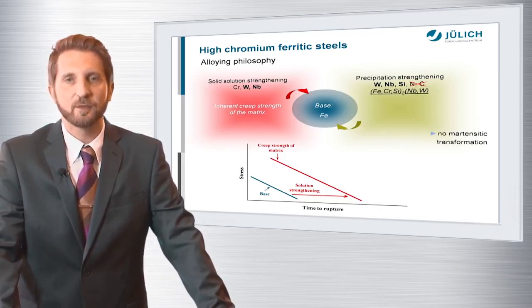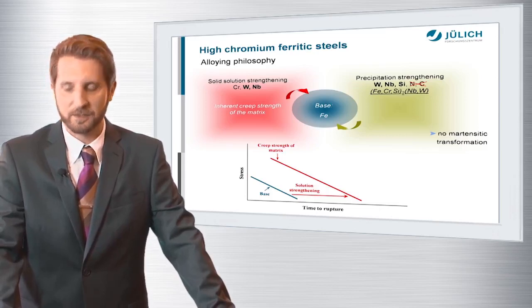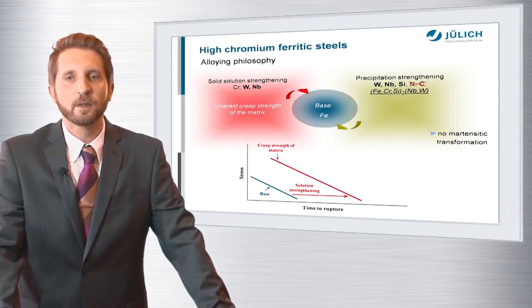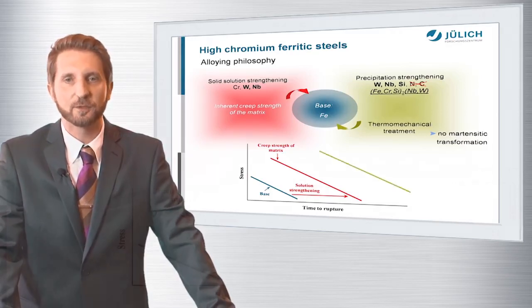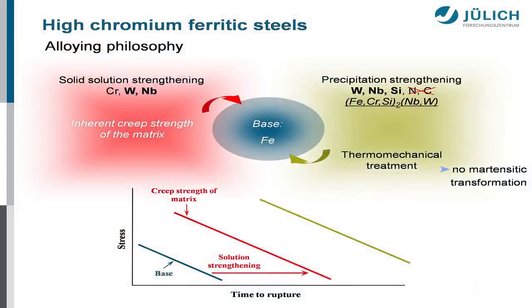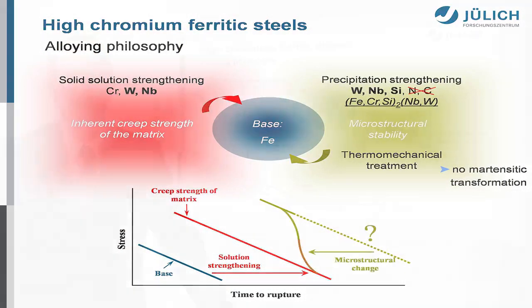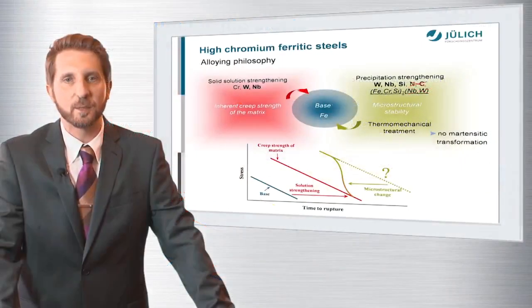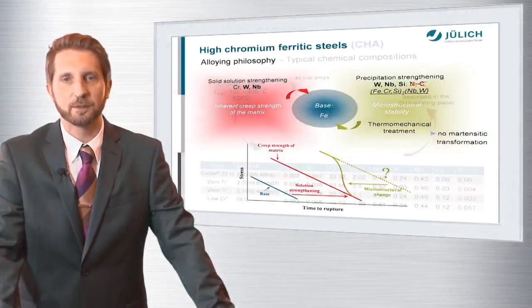And that means that if you want to go for enhanced dislocation strengthening, like it is done in the martensitic steels just by the martensitic transformation, you have to go for specialized thermomechanical treatment. And this gives another great leap in creep strength, but for sure, like it always is in high temperature materials, whether this boost in creep strength is really stable is a question of microstructure stability in the long term.